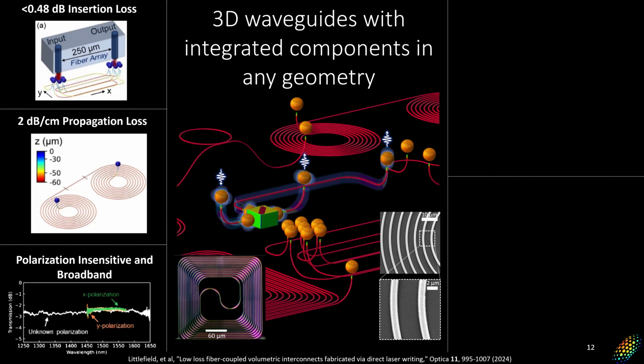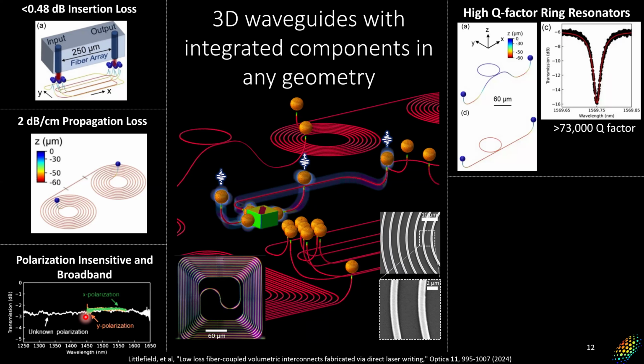And then these optics are very polarization insensitive and broadband. This is showing a range from 1250 to 1650 nanometers, but this has actually been tested down to like 780 or something like that. Again, you get pretty consistent loss in that range until you start getting to the range where you're getting a lot more loss from the Rayleigh scattering that I mentioned.